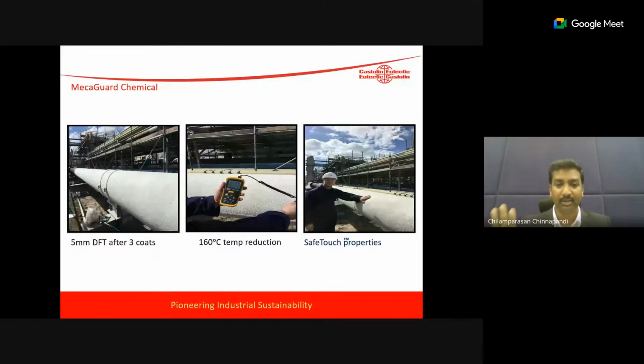It can be done online at 300 degrees also. If there is any pipeline, no problem. We can do online coating of the pipe to avoid traditional thermal insulation. And the life will be up to 10 years. If there is any inspection to be done, it can be removed and they can check the pipe thickness also, and you can do the recoating by yourself.